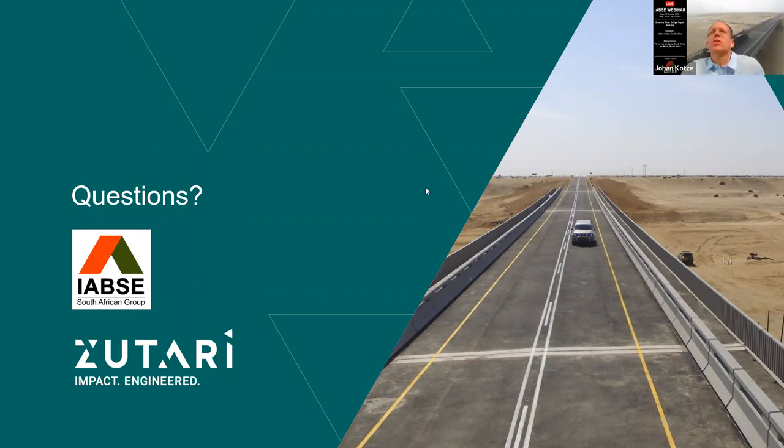So I think the biggest issue, and to come back to the concrete question also, the fact that we painted the concrete in the end was really just an additional measure to ensure the durability of the bridge. The main issue with this type of defect, what we saw, was that you need to keep water away from concentrating on points on the bridge. So the biggest issue here for me is the drainage system that needs to be in place always.